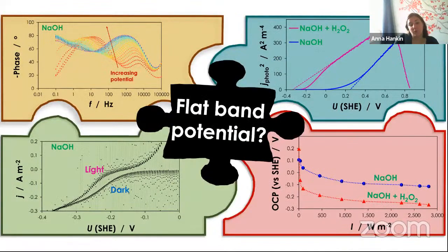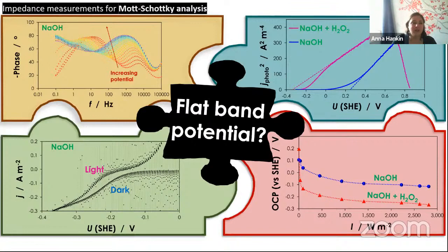So one study I did on just one type of hematite material, the one that took 6 years, was all in the pursuit of this flat band potential, because I wanted to know what to put in my model. And I couldn't ever get a reproducible result. And there are four main methods that can be used for determining this flat band potential. And by far the most complicated of the lot is the one that people use the most.